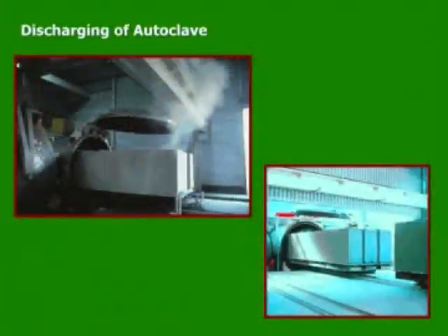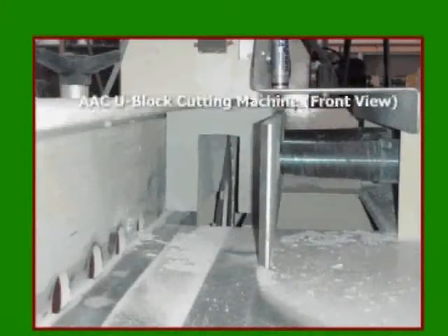After about 10 hours the material is ready for discharge. The material has approximately 30% water content. During transportation, delivery and installation, it will lose approximately 15%. The normal and healthy water content is between 4 to 8%.